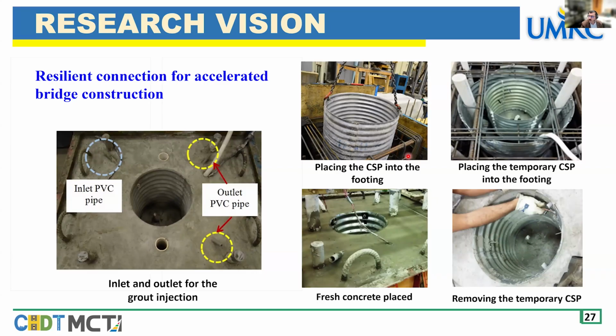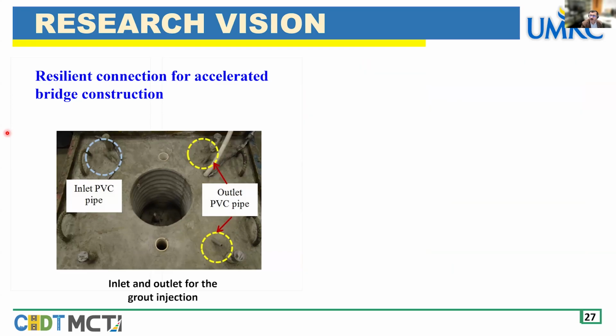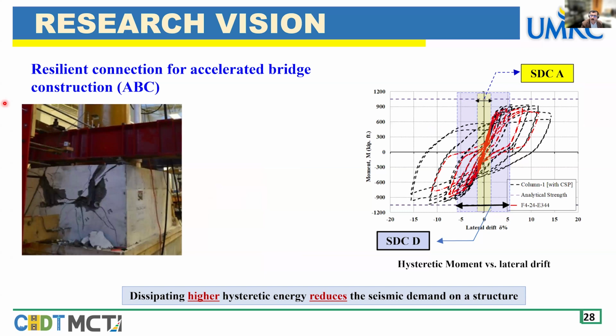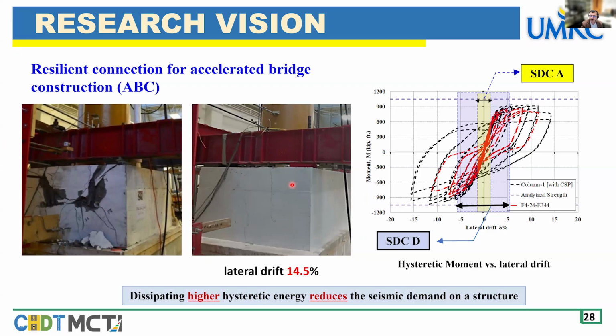So with this corrugated steel pipe we achieved more confinement for the embedded steel tube, in order to achieve full inelastic deformations under the cyclic event. After this, as you can see here, this is the footing without the corrugated steel pipe, and this is the footing after inserting the corrugated steel pipe. And we reached up to 14.5 lateral drift capacity. With this 14.5, as you can see, this is the column without any significant damage, just hairline cracks, as you can see here, compared to the footing without the corrugated steel pipe.